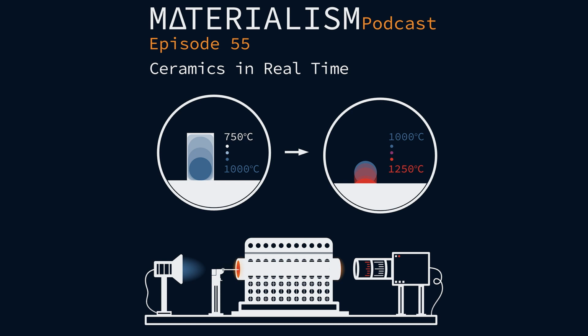If you develop your procedure, your thermal cycle, your thermal treatment, then you must verify that if the furnace, because it is not so exact, an industrial furnace, is 20 degrees above or 20 degrees below, it will not destroy the piece, okay? It still goes, okay? Then you can study the compatibility between your substrate and the glaze before going into production.